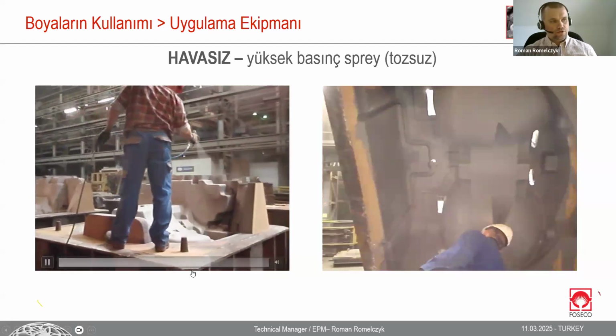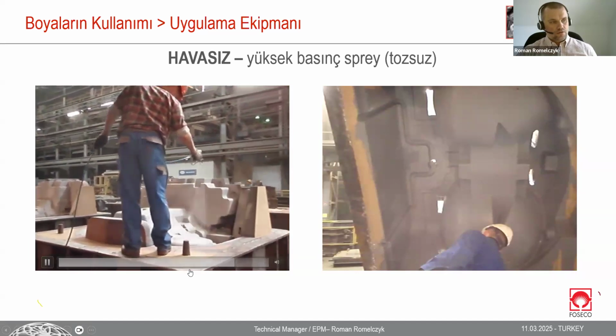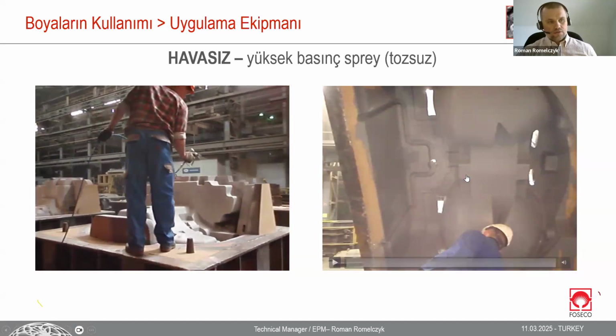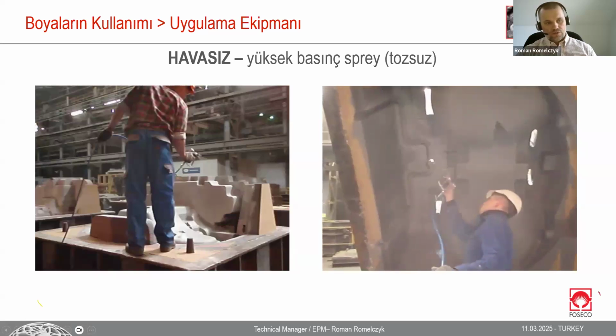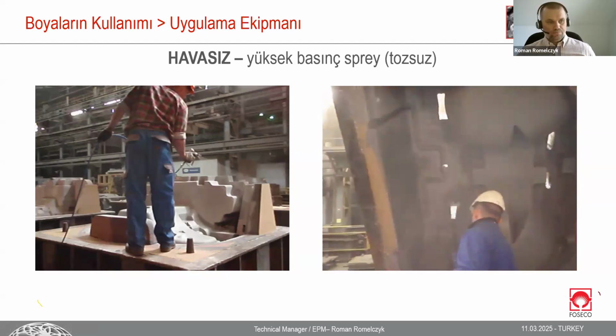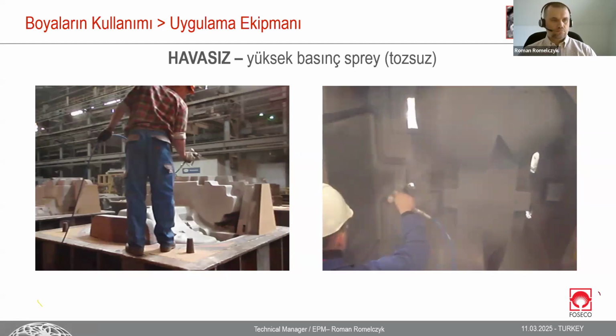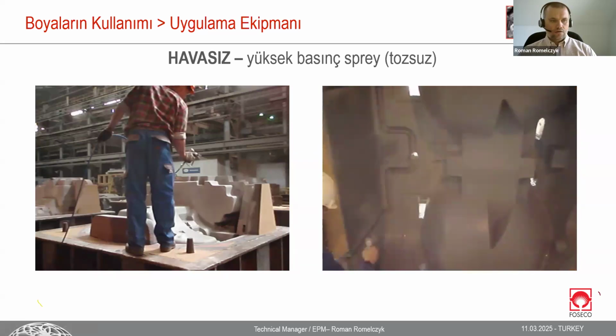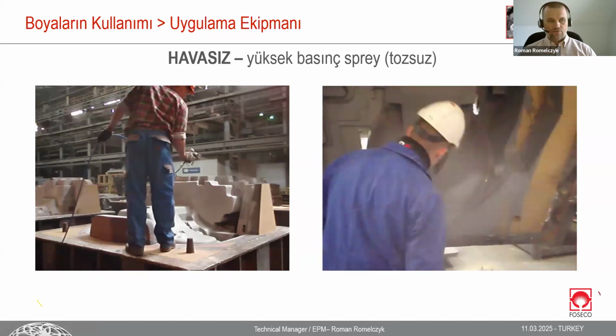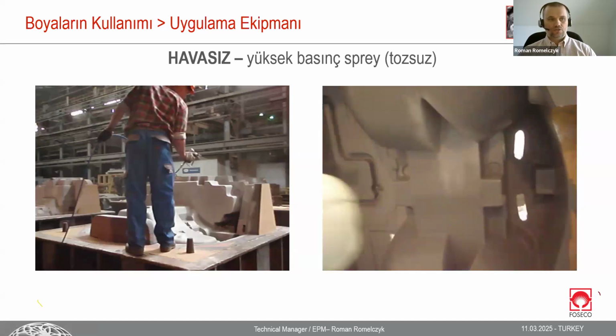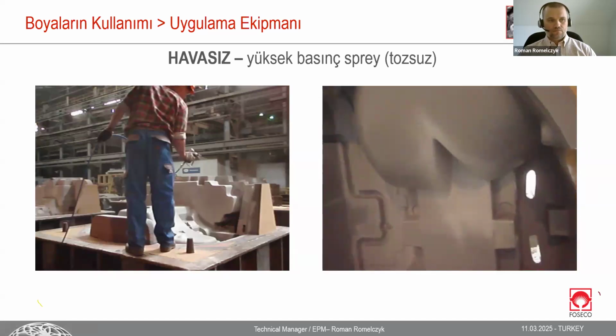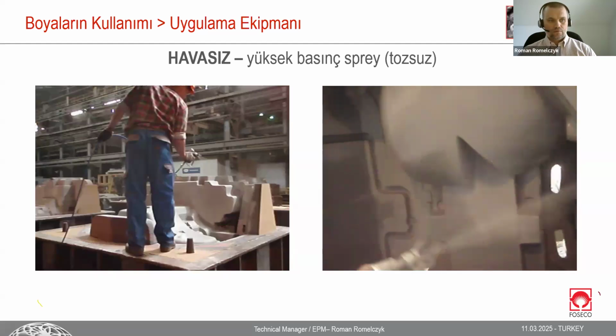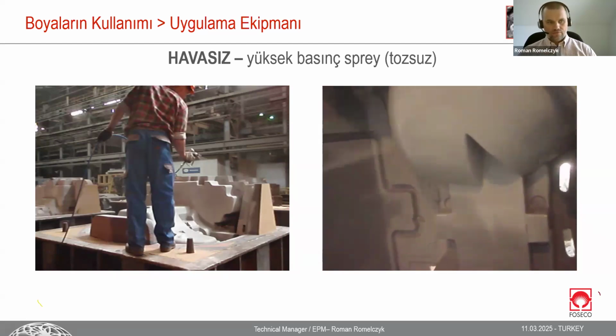So as you can see, it's very easy, and the layer is applied very fast. On the right side, it's exactly the same mold, but the top part. The first layer was applied by flow, and to improve the wet layer thickness, the final layer was applied by spray gun as well. You can see how it looks, how precise it can be, and fast as well. This application gives you a chance to apply some 1.2, 1.3 millimeters of coating that fast. And now it's applied some 0.25 average, very fast.